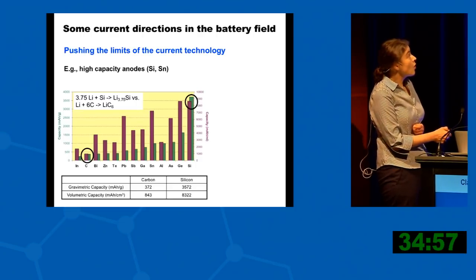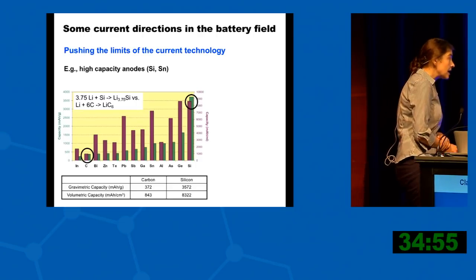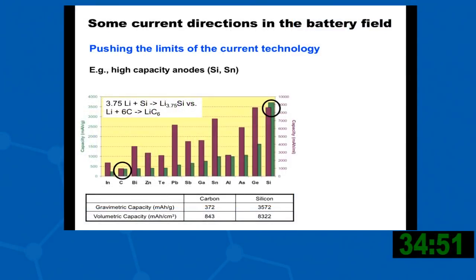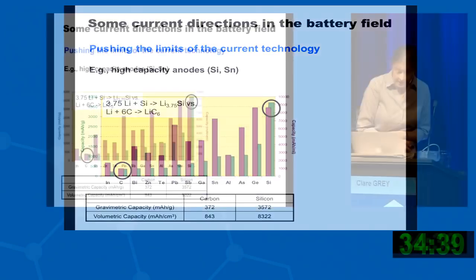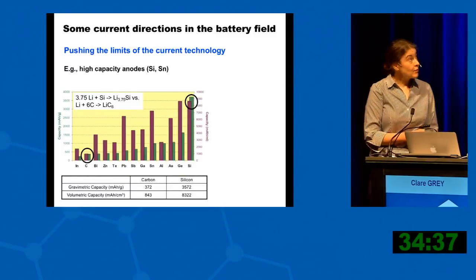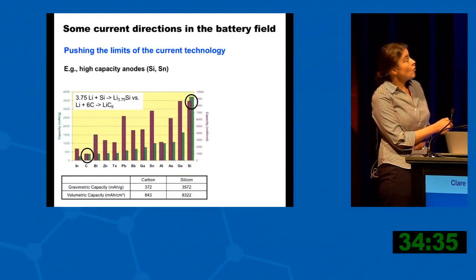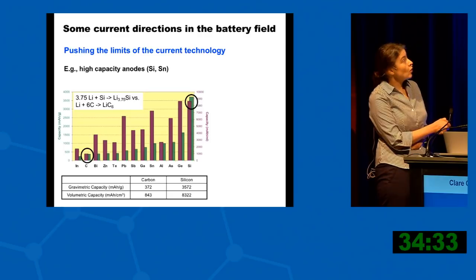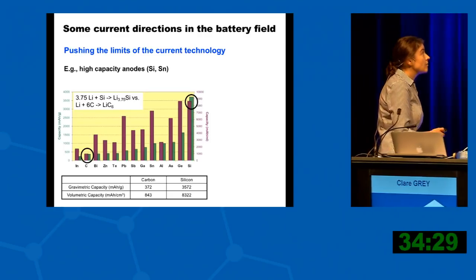There's a lot of work on pushing the limits of current technology, improving the layered materials we have on the cathode. And on the anode, a lot of work has gone into trying to replace the graphite in our standard batteries with silicon. The reason is that you can get an almost 10-fold increase in capacity by reacting lithium with silicon: almost 4 lithiums reacting with 1 silicon atom, as opposed to 1 lithium reacting with 6 carbons.